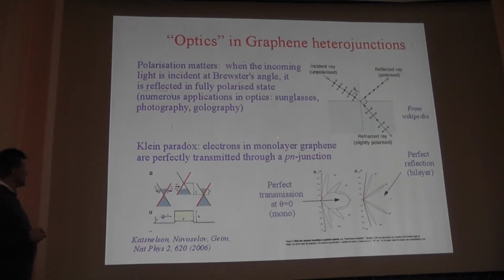There is a phenomenon called the Klein paradox, first considered in the condensed matter context by Katsnelson, Novoselov and Geim. So they've looked at the standard quantum mechanical problem of transmission through a barrier. They have shown that if the particles are normally incident on the barrier, then they are perfectly transmitted. The transmission coefficient is 1. Nothing is reflected. That happens precisely because particles have polarization.